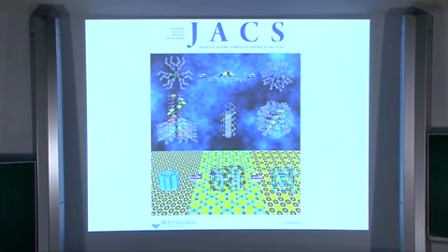The simplest fragment of graphite is called triphenylene, and triphenylene never wants to form a spherical object. They will form columns. They pack one on top of each other at the pi stacking distance. We attach the dendritic molecule, and the object forms a helical structure immediately, a rod-like helix, and as a function of temperature forms a globular object that is also helical.